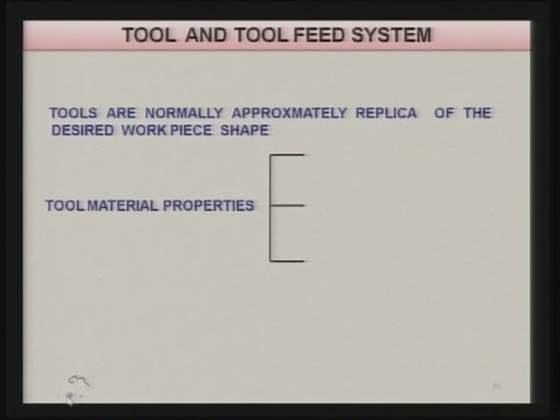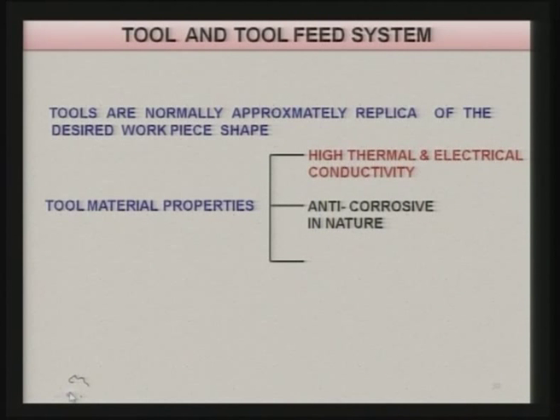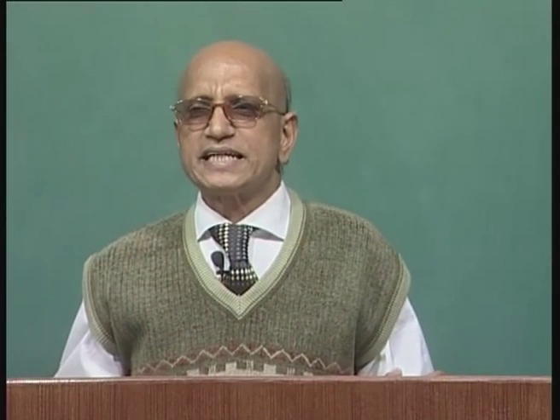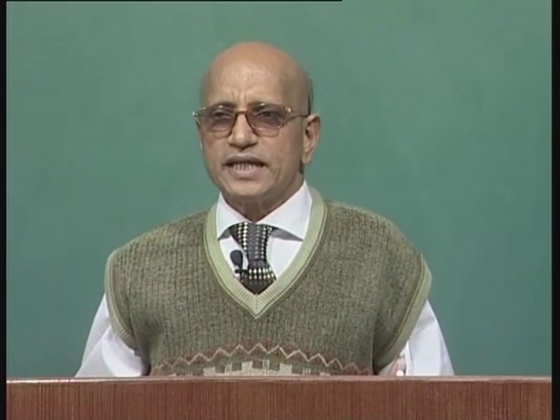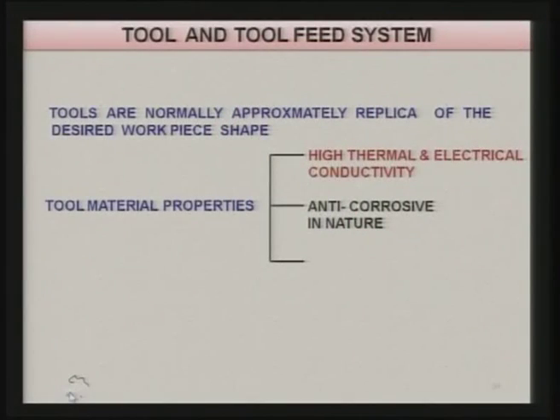Selection of tool material is very important. The tool material should have high thermal conductivity and high electrical conductivity. Thermal conductivity is important so that the temperature of the electrolyte does not rise to a higher level; otherwise the conductivity of the electrolyte will change, and you will not get the desired work piece surface profile because conductivity differs from what was used during tool design. Electrical conductivity should also be high; otherwise low electrical conductivity leads to higher heat generation.